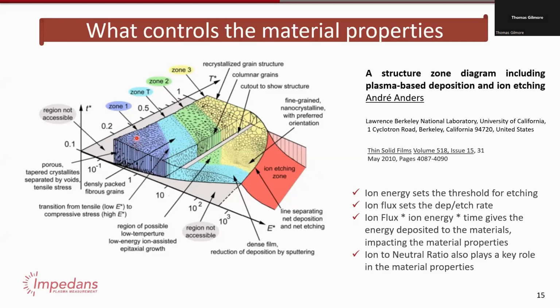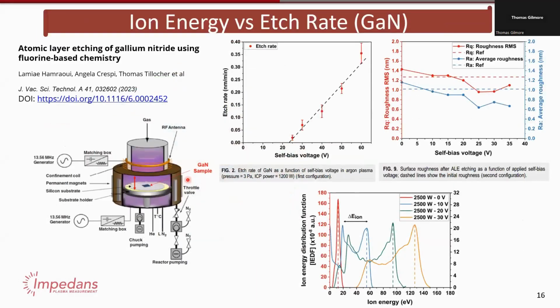Amorphous and crystalline silicon will depend on these sort of parameters as well. Let me give you some just practical examples here. So here, this is ion energy versus gallium nitride etch rates. This is by this group here. So this is the tool layout. It's an ICP tool, and you have the sensor down here, and you have the coupon down here. And what I wanted to show you is, if you look at the etch rate versus the self-bias voltage.